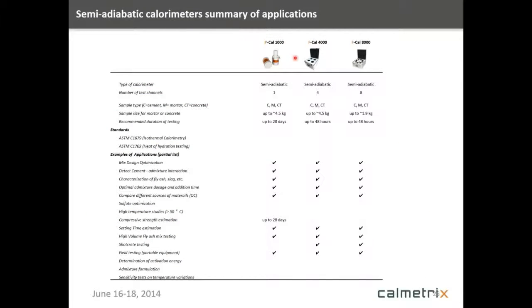In terms of the semi-adiabatic, we talked about the two different models of the FCAL devices, the 4-channel and the 8-channel. We also manufacture what we call the PCAL 1000. This is actually not available to buy. It's available on a rental basis. All three of these are semi-adiabatic. The PCAL is really the device that simulates most mass concrete. It's basically a sample of concrete that's completely enclosed in an insulated container. The FCAL devices most simulate what would happen in a slab. So you're insulated on the sides and the bottom, but the top of the sample is basically not insulated. So this is more analogous to a slab.